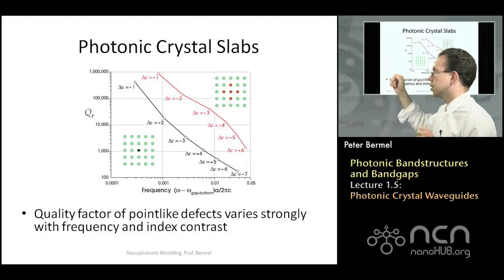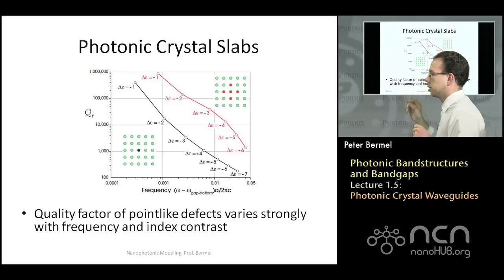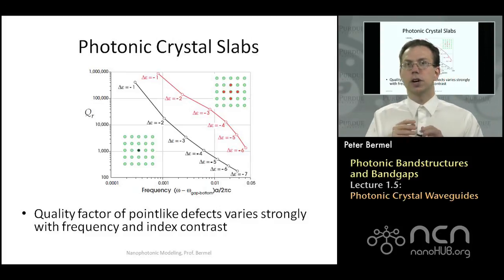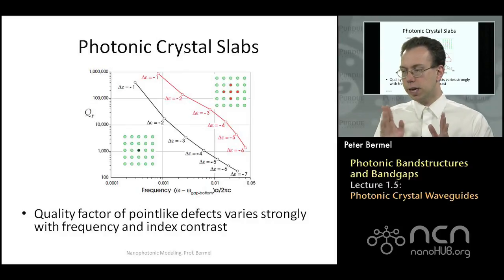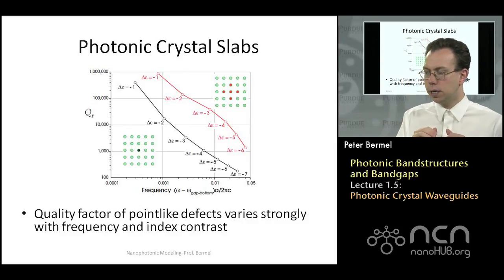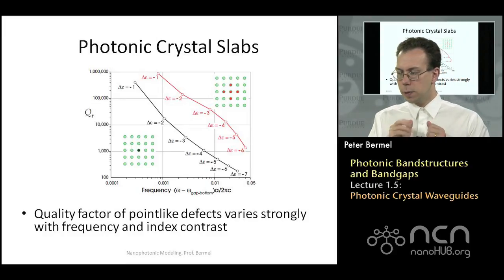And then the other thing about that trade-off you can see here is that the cross-like pattern or structure behaves much better. So you get about a factor of 10 or so in the quality factor associated with having this cross, and the corresponding factor of 5 type delocalization that's introduced using this cross method.